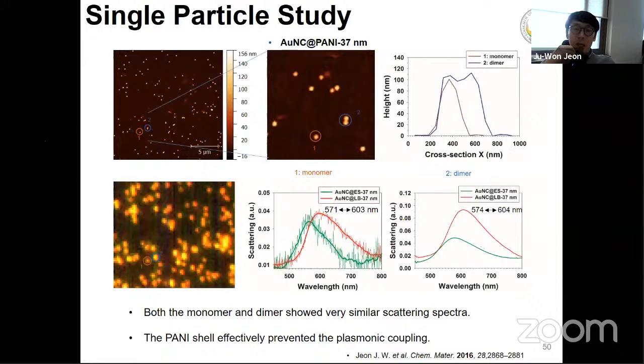And by using a different method, hyperspectral imaging, we tried to find the exactly same spot. So this is the L shape, and we successfully found the L shape, and this is the arrow shape, and we found the arrow shape. And this monomer corresponds to this one, this dimer corresponds to this one, and these are also the same shape. So we converted the ES to the LB for the monomer and dimer, and it shows a very similar position, which means this kind of aggregation is not affecting the LSPR property because the polyaniline acts as a physical spacer to successfully prevent the LSPR coupling.